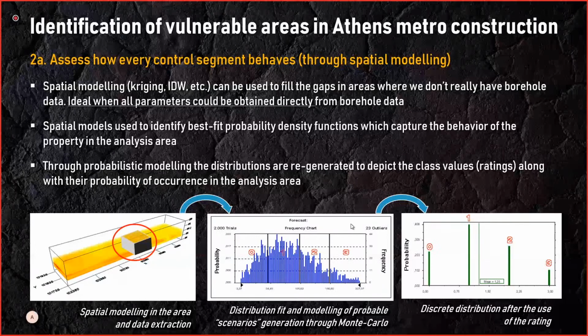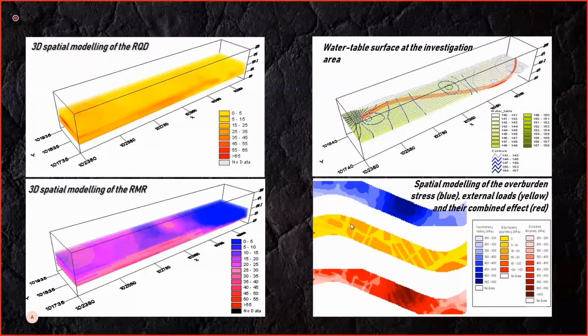For example, in the slide, you can see that we have a probability of occurrence for class 0, which is very adverse conditions, of the order of 20%. We have a probability of occurrence of class 1 of approximately 40%, class 2 approximately 30%, and class 3, which is the most advantageous one, approximately 10%. So in this manner, we can have all the spatial data constructed into ratings that are going to help us make the whole assessment.